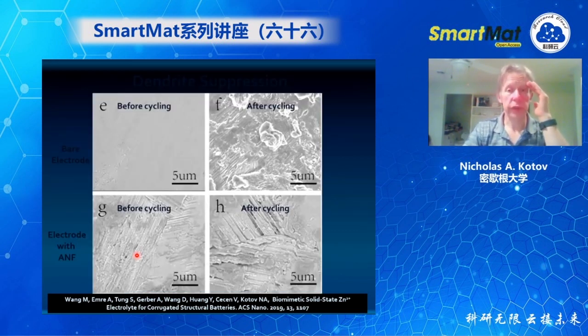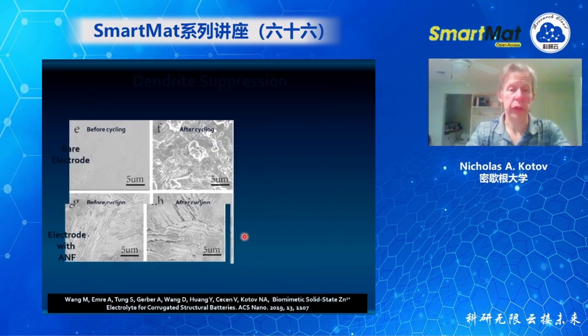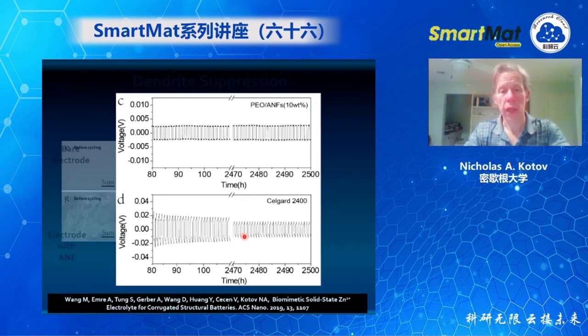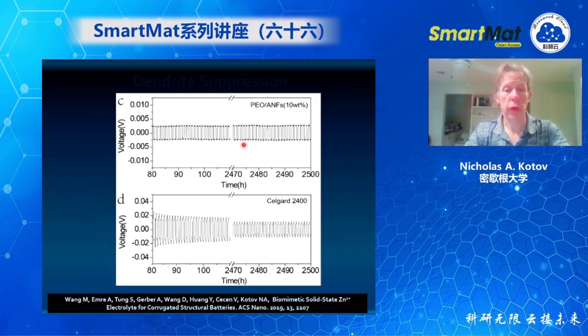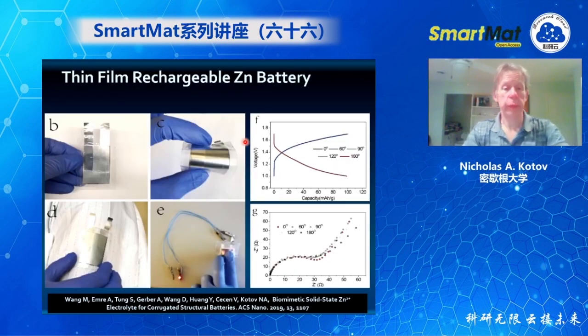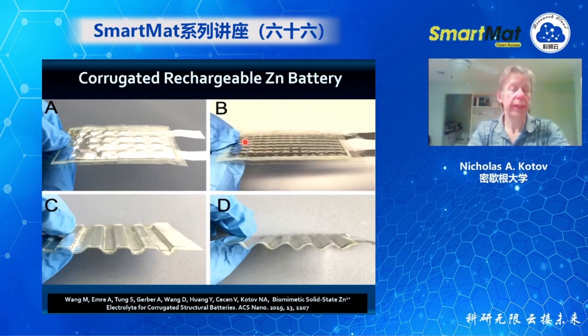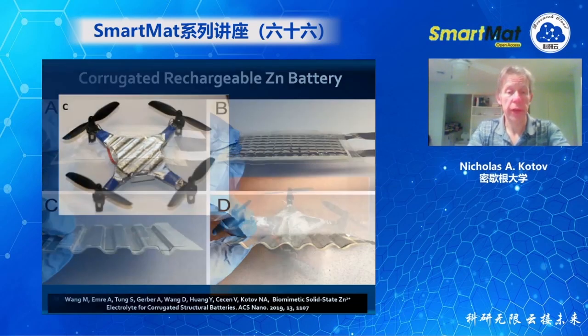And indeed, we saw that if we don't use our separators, the dendrites are growing very rapidly. But if we use them, then we don't have almost any dendrites at all, which can also be observed in the electrochemical data. The batteries remain flexible and can be corrugated after the preparation of the battery, so they're safe.